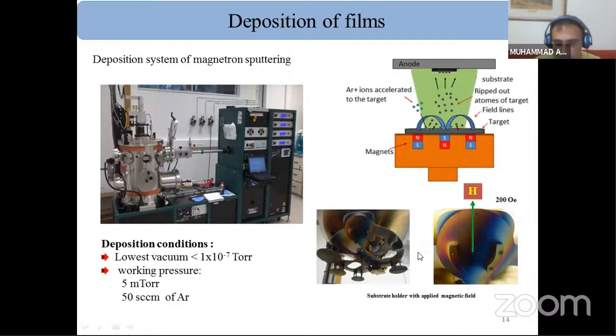Here we can apply a uniaxial anisotropic field of 200 oersted. This is a deposition system of magnetron sputtering, where we can place our samples. Depending upon the quality of the thin film, we can vary the working pressure during deposition, and we can also vary the argon pressure in the vacuum chamber.